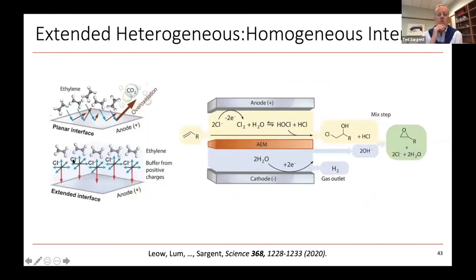And our concept here was that we would try to get to high current density by using a kind of redox strategy or redox mediator approach. And we thought that we could potentially then run at high current densities without over-oxidizing. And essentially we build a kind of delocalized or extended heterogeneous homogeneous interface and thereby also overcome mass transport limitations without having to go to such high potentials that we were producing these kind of runaway processes where we couldn't control the oxidation and limit it just to the ethylene oxide.